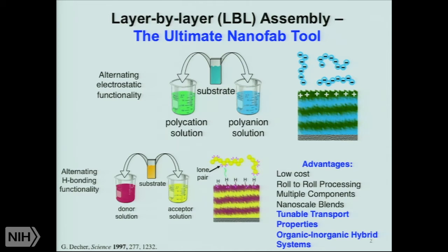until ultimately the surface charge gets reversed. And at that point, electrostatic repulsion prevents any further deposition on the substrate. So you have something like a monolayer that is controlled. It's a self-limiting adsorption. And the thickness of that layer is dependent on what you're adsorbing, if it's a polymer chain or a nanoparticle, for example, and the pH and ionic strength of the solution that you're adsorbing from. So you can make these films thicker or thinner based on those kinds of conditions.